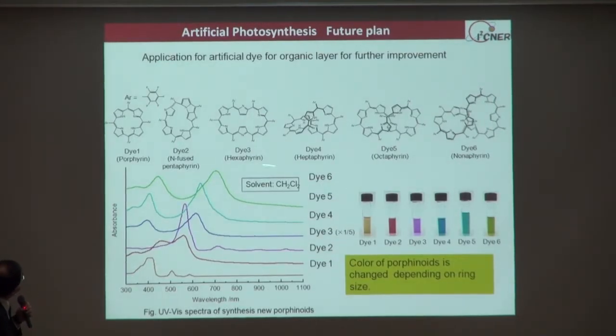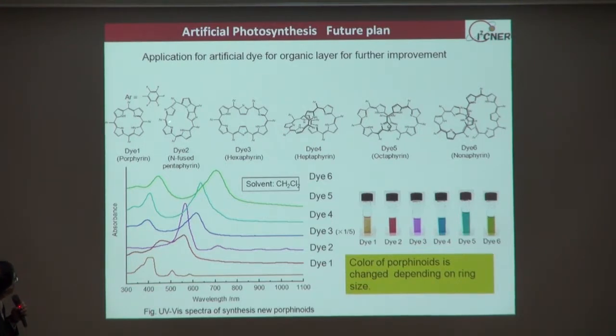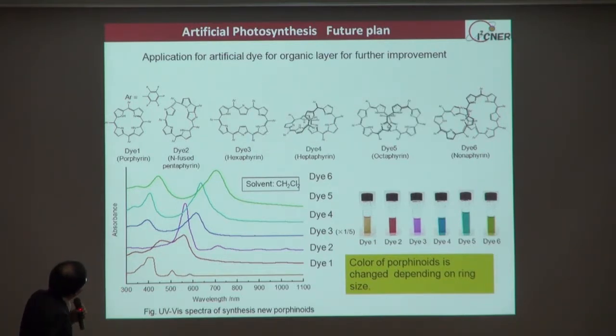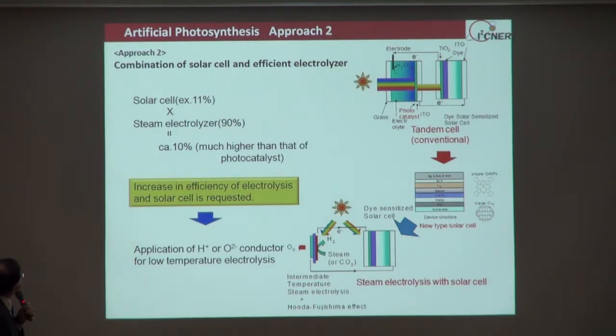And the future plan is shown here. We have now successfully collaborated with the organic synthesis groups, and we very successfully synthesized these kinds of new dyes. The color of this dye is shown here, and with increasing number of this ring, the color changes to more red shift, and then we can use further longer wavelengths for the excitations. And up to now, we used this compound. This compound is very similar to the chlorophylls, which are used for the current photosynthesis. But by increasing the number of this ring, we can use further longer light for the excitations. And data will be reported in the next annual symposium or some symposiums.